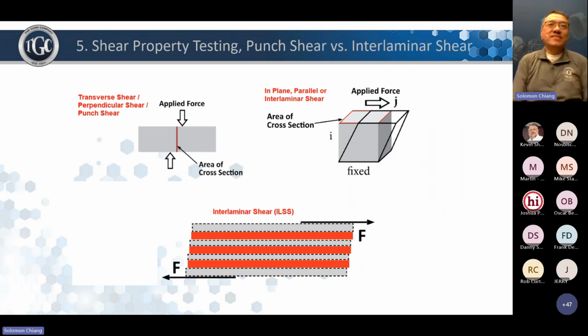The last one, not as popular as the other four, but it's important for design work, not just the product design, also the manufacturing method. Say if we are punching some heavy gauge thermoset laminate, then we want to make sure that our press has enough tonnage to do the job, and we can use what we call the punch shear strength. Punch shear is at the top left-hand side, essentially. We apply a force to punch through perpendicular to the lamination. So we find out what that is in PSI or KSI, multiplied by the total shear area of the component. And then we know what kind of press, what kind of tonnage we need. Obviously, we need a safety factor.